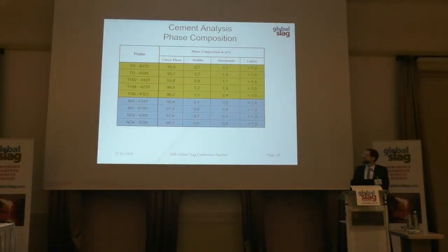Coming to the next analysis, this is the glass content. Glass content is a very popular factor that will often be used for the quality of granulated blast furnace slag. The blue rows are the wet granulated slag. The yellow rows are the dry granulated slag. If you build an average of these values and these values, you can see that we have a remarkable difference between the dry and the wet granulated slag.